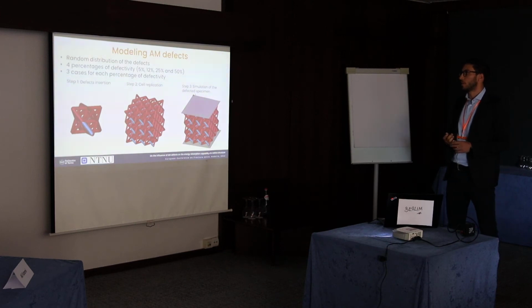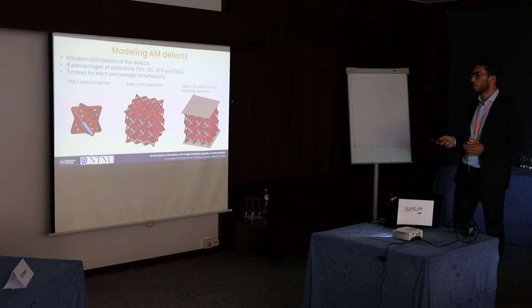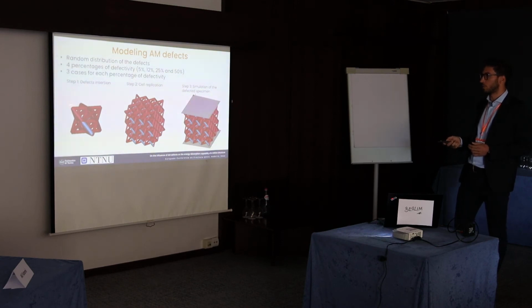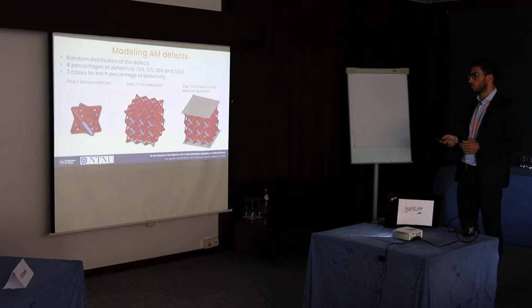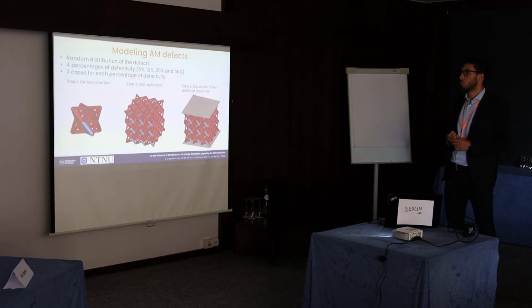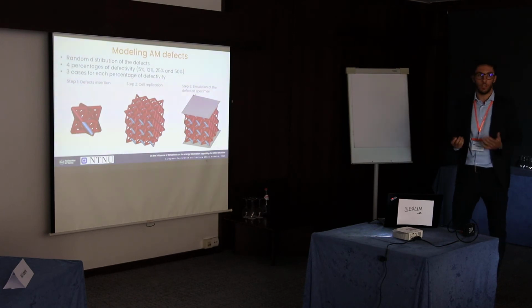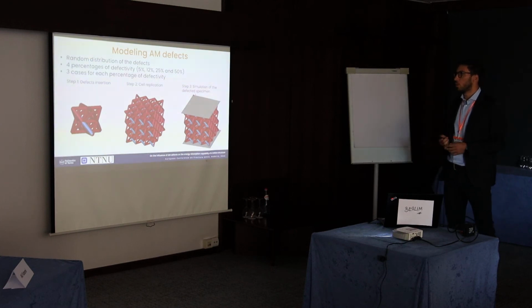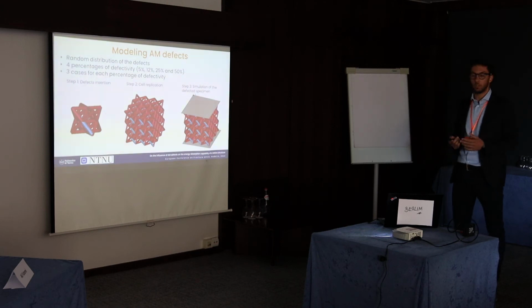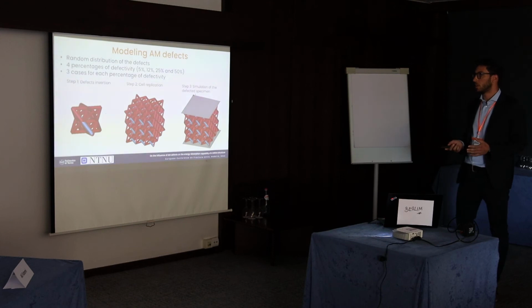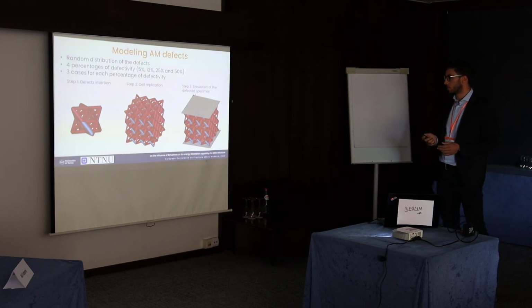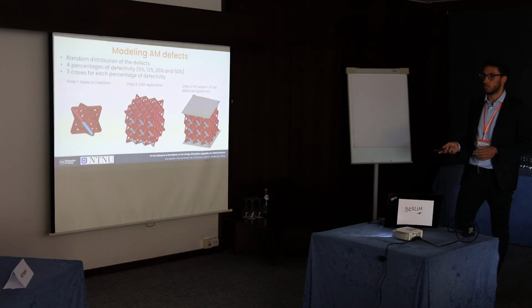Also, we considered different percentages of defectivity by inserting different numbers of defective beams within the unit cell. Then for the construction of the specimen, we just replicated the unit cell with defects, and then we performed the simulation. To investigate the effect of the location of the defects within the unit cell, we considered 3 different cases for each percentage of defectivity by randomly distributing the defects within the unit cell and then replicating and simulating. So in total we performed 12 simulations for each kind of